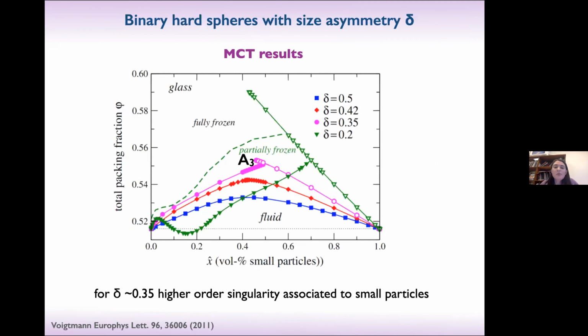So the first one I want to mention, because we will use it later, is binary hard spheres. These are MCT calculations of Thomas Voigtmann, in which he was able to show that there is an A3 singularity, and now the control parameter that before was the well width or the width of the potential now is the size of the small hard sphere. So we have larger spheres and smaller spheres that are 35% smaller than the large ones.